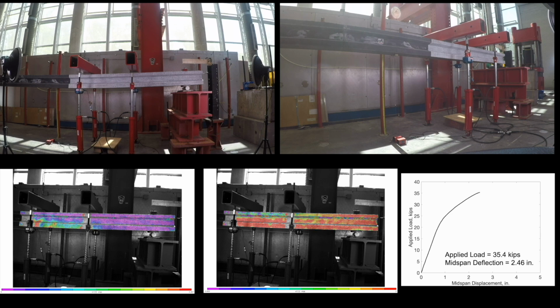You can see our beam has deflected substantially. We're seeing large tensile strains shown in red under the second load point, which highlights a wide crack forming. What's really interesting to see is that if we look at the principal tensile strains, there's really only one crack that is formed at peak load, which we can see from the red color on the plot. This is uncommon for traditional concrete flexural members and is related to the vastly superior bond strength of UHPC.